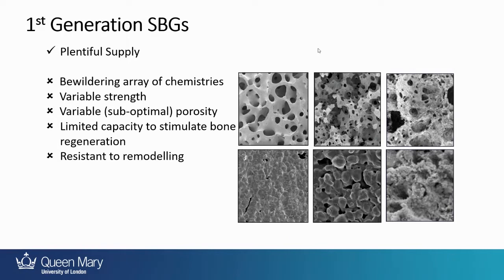where he said 100 microns was a good size for a pore interconnection. The pore interconnection is the size of the holes between the pores. And this was related to the fact he was working with polyethylene, and you needed to have a big pore interconnection size because polyethylene is a near inert material. You've got fibrous encapsulation of that material, and you needed to take that into account as well as bone regeneration and space for vascularization. So in fact, if you've got a bioactive material, you probably don't need pore interconnection sizes as large as 100 microns, but you do need pore sizes that are reasonably sized. You want them to be actually probably more like 500 microns or so. So don't believe everything you read in research papers. Sometimes people misinterpret things, and then that becomes groupthink and gets carried on through the literature.